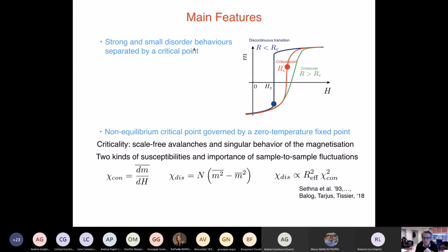Depending on the disorder, there are two very different behaviors, one smooth and one discontinuous, and between the two there is a critical point that has been studied a lot by Sethna and collaborators. This critical point is interesting because it's a non-equilibrium critical point, governed by what is called a zero temperature fixed point, which means that the disorder is relevant. The disorder is the most important feature at this critical point. So the temperature is renormalized to 0 at large scale.